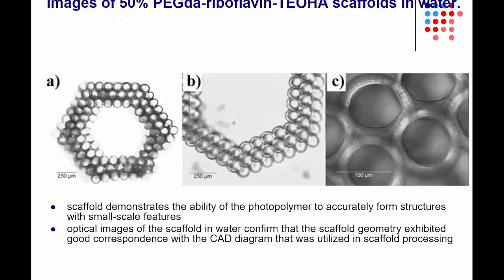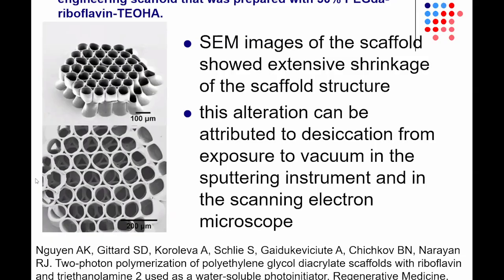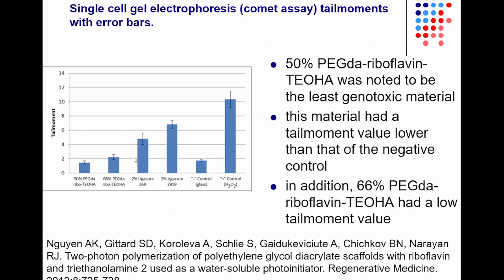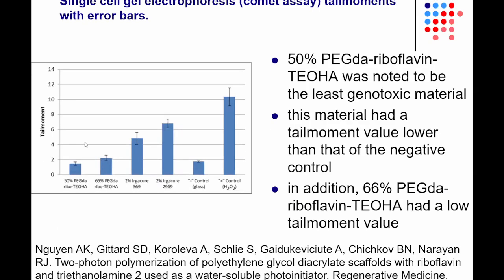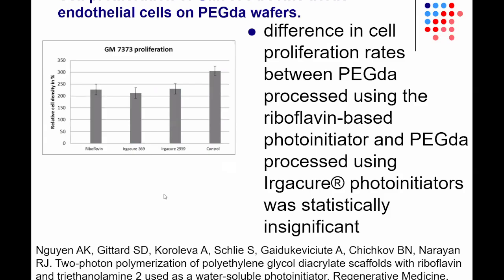You can see here that we were able to polymerize these scaffolds with this combination of riboflavin and triethanolamine as the photoinitiator. You can see here good feature-to-feature uniformity in these polymerized structures. You can see here that this material is very friendly in terms of genotoxicity studies. It has the lowest genotoxicity, similar to that of glass, much less than the genotoxicity of conventional photoinitiators. You can also see here good amounts of cell proliferation.